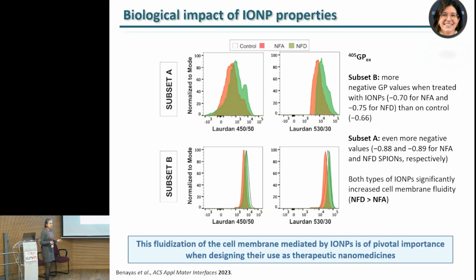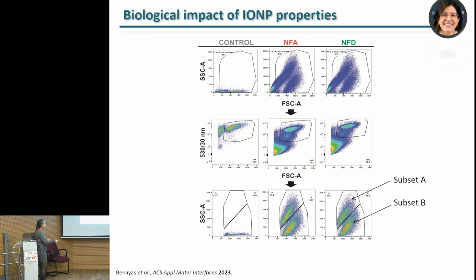Because of this close interaction, we thought, okay, is the cell membrane being affected? Because we are really seeing a lot of nanoparticles inside, around the cell. So is this affecting the cell membrane? And indeed it was. As you can see here, we use this GP index, that is an index that tells you about the fluidity of the cell membrane in the different populations. We have here the subset A.